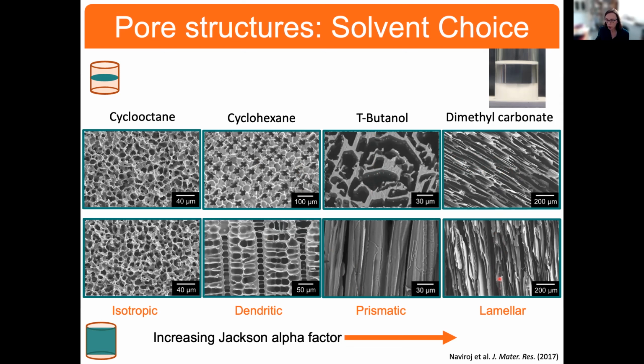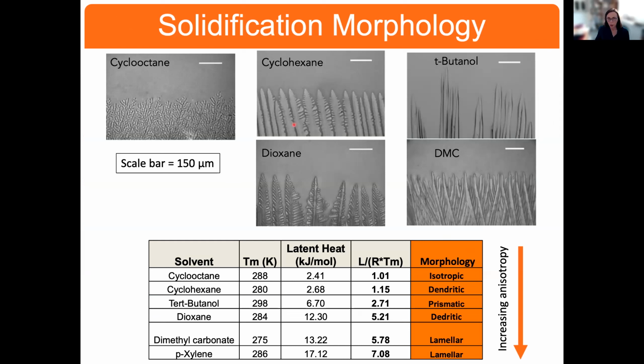If we were to look at this with water as a solvent, that fits in this region as well. So just to confirm what we were seeing in the solid, we also did some imaging watching these crystals grow. And you can see from this set of images that these do correlate very nicely with the pore structures that we saw. With the cyclooctane, these are known as seaweed structures that